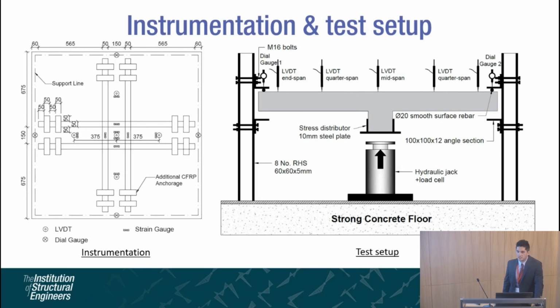We developed this testing rig to test the slabs. The load was applied from the bottom. As you can see, the boundary conditions were free to rotate by placing smooth surface rebars. Steel angles were placed, but they were showing some level of deformation, so we measured its deformation by positioning dial gauges, and we took this into consideration during our analysis. After the testing, all of them were tested under punching shear until the failure point.